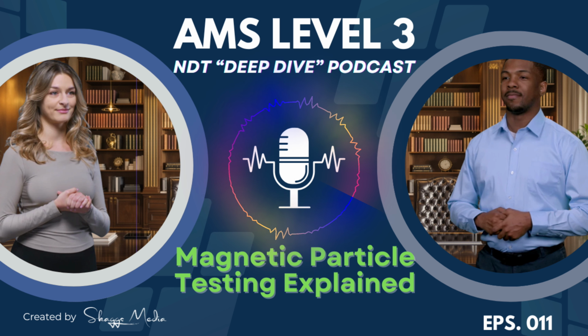What's really interesting is that these pulses give the magnetic particles extra mobility. It's like they're getting jiggled around a little bit. This helps them migrate towards even quite weak leakage fields and build up an indication. It really aids formation and helps avoid non-relevant clumps. That makes perfect sense. A little vibration helps the dust settle exactly where it needs to.